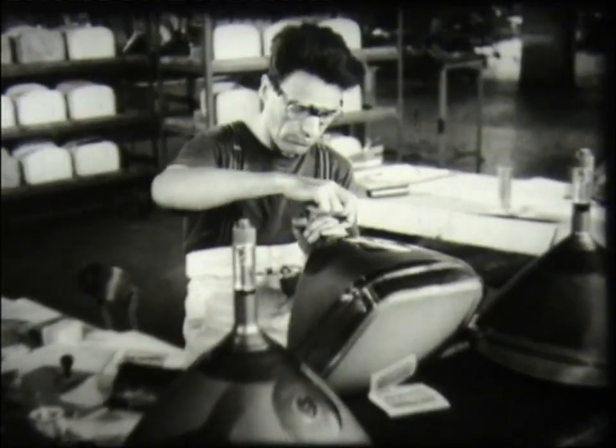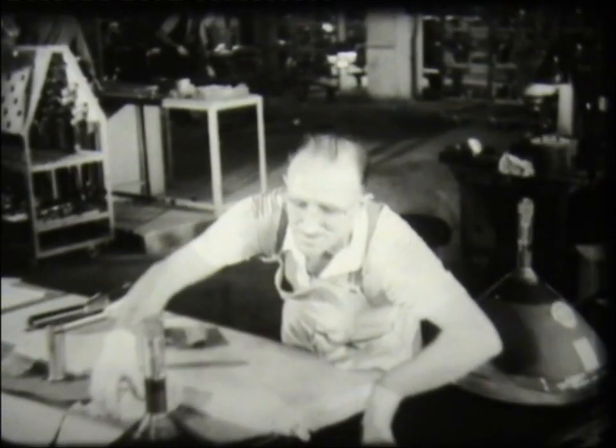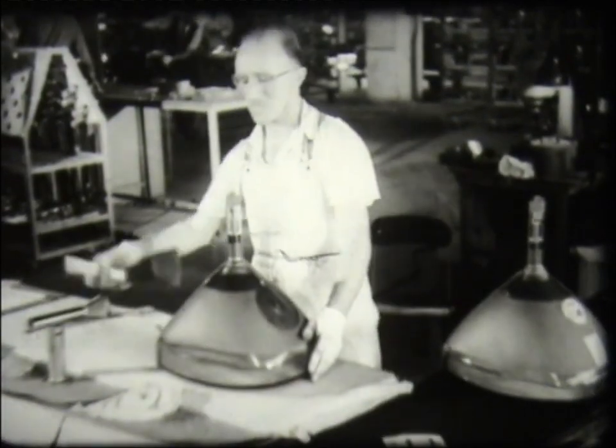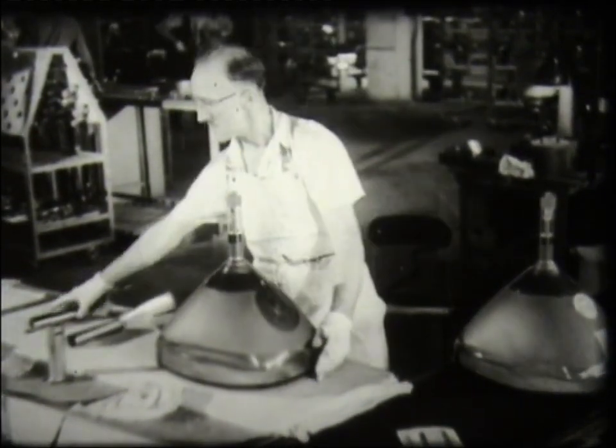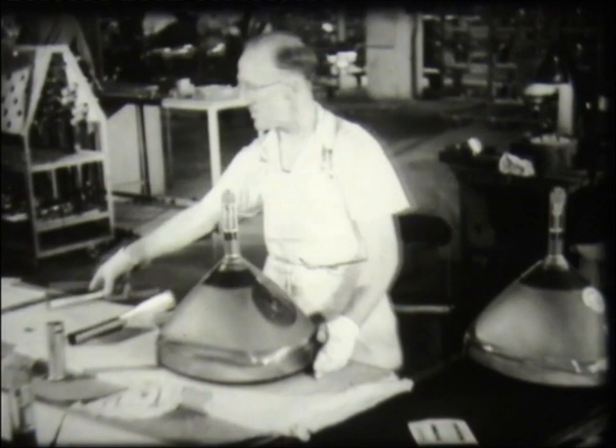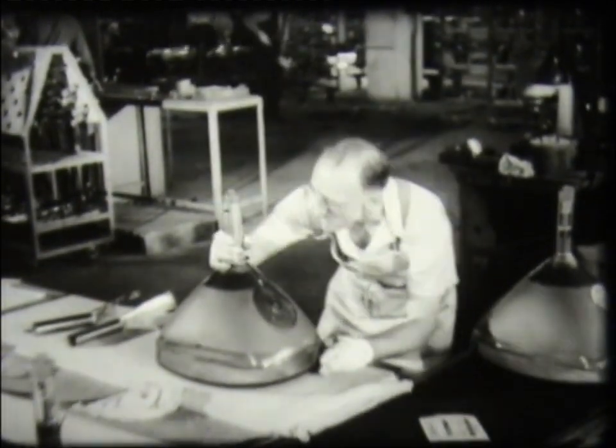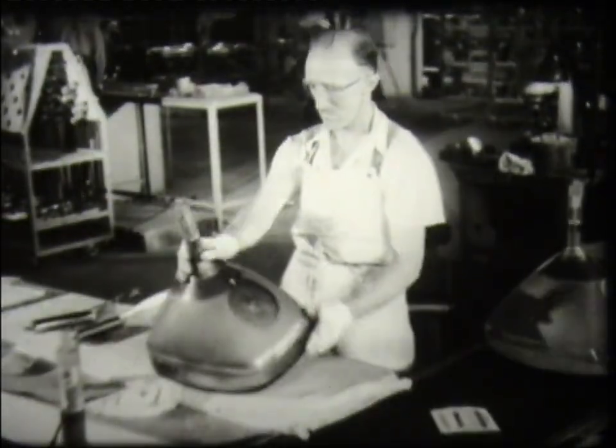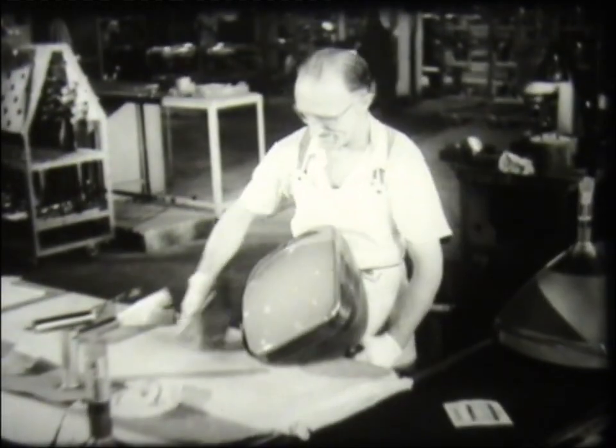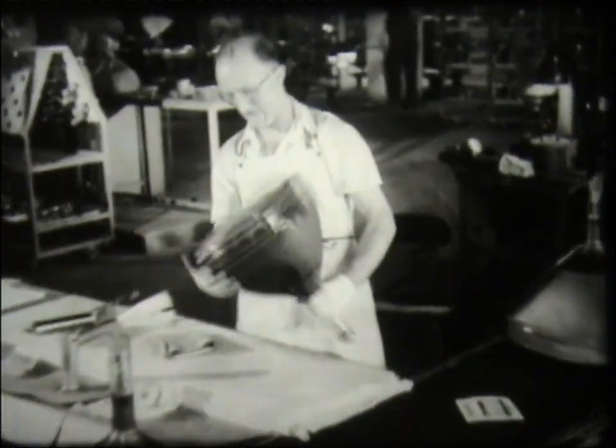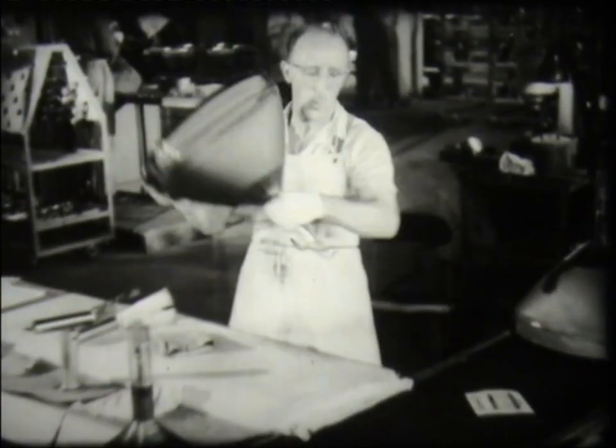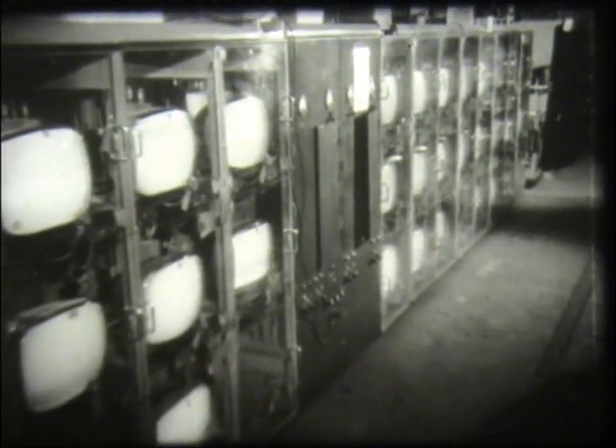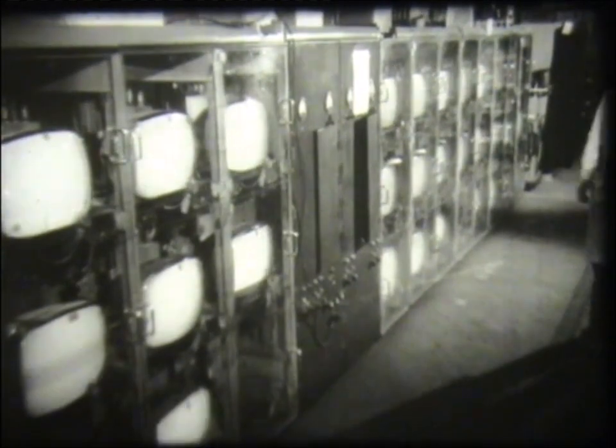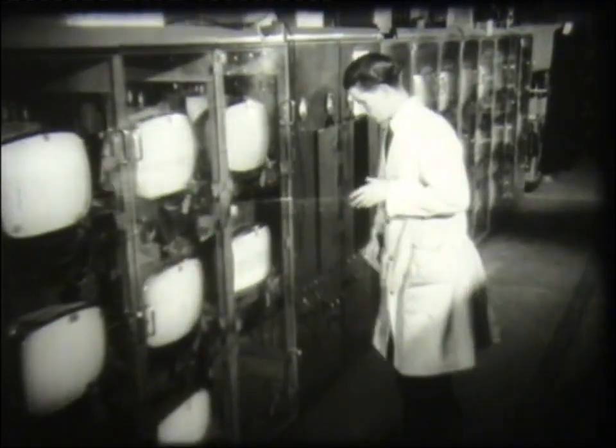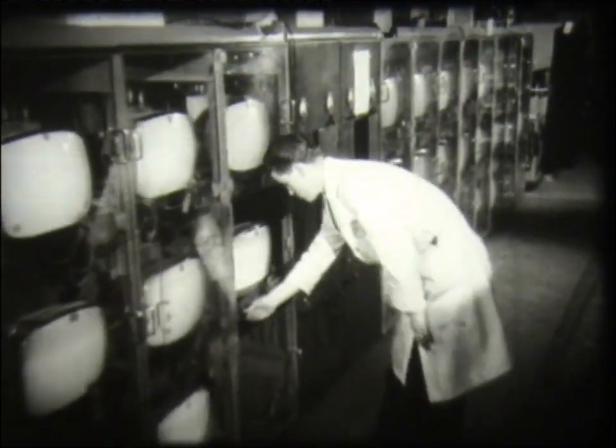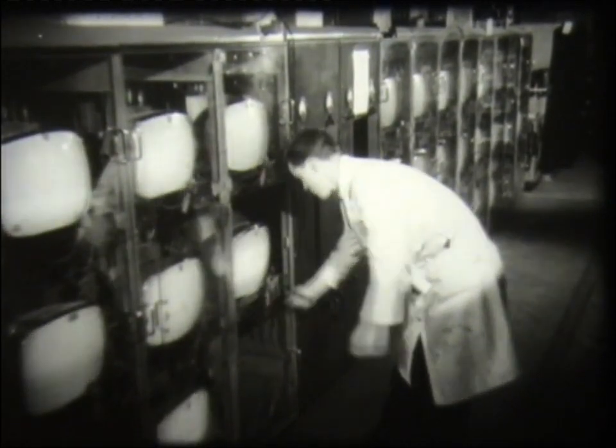With the marking of the type code, the actual manufacture of the tube is now finished. But once again, every tube is thoroughly inspected. Even this is not enough to satisfy the Quality Control Laboratory. Finished tubes are taken at random from the end of the production line and subjected to more than 40 laboratory tests. By comparing the results of tests on successive batches, any trend away from normal is quickly detected and reported to the production department, so that steps can be taken to rectify matters before quality is adversely affected.